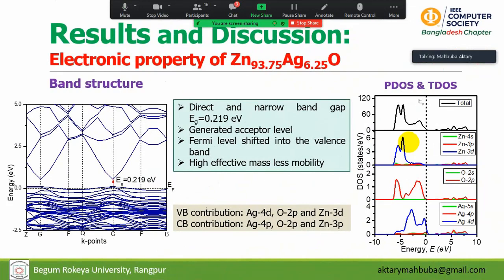And electronic property of silver doped zinc oxide. Here we can see again on the left side of the band structure diagram, and it has the lowered band gap value 0.219 electron volt with direct band gap. Since it has the same momentum value G, and transition is direct, so it is a direct band gap semiconductor, and a new acceptor level is generated above the Fermi levels and near the valence band, which is the strong evidence of the existence of p-type conductivity.